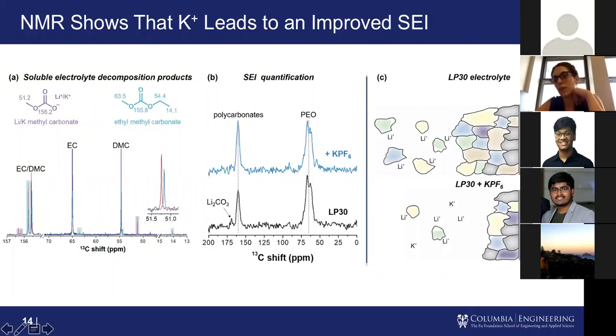So this is sort of a cartoon picture of how we think these SEIs are different. Overall, we have less decomposition whenever we have KPF6 present. So we have a thinner layer here. It's probably helping us get better ion transport to the surface. There's not as much gunk to wade through for the lithium ions whenever they're trying to be deposited. And we think that this helps us get better deposition behavior.